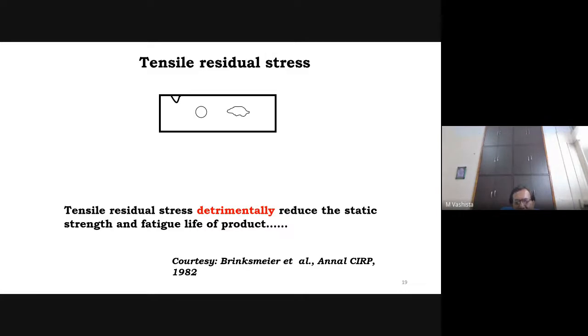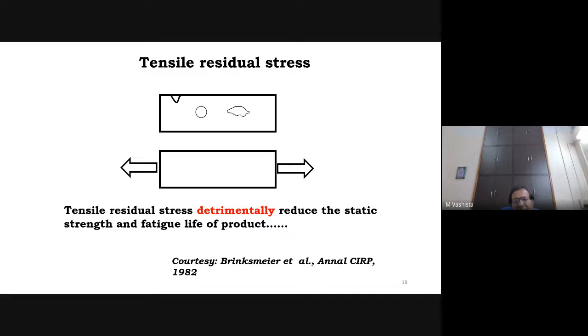Why will they create the problem? Because if the component has tensile residual stress, it means it is in a stretched condition. This stretch or tensile nature will elongate the crack, it will elongate the void, it will elongate the porosity. When they get enlarged, then definitely the fatigue strength or static strength of the material will get reduced. So this is very detrimental for the service life of the component.